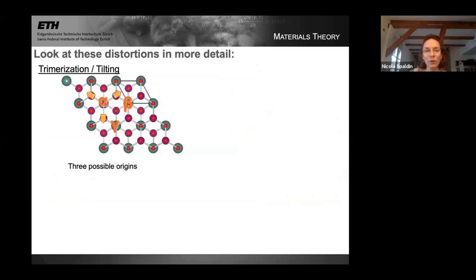to trimerize around. Then origin beta, which was previously equivalent to alpha, is excluded as a trimerization center, because to trimerize around beta, this oxygen would have to go up and left, and it's already used up going up and right. And likewise, origin gamma is not available as a trimerization center, because that would require this oxygen to go up and left, and it's already used up going down. So I have three possible choices of origin that I can choose to trimerize around. So this should give me three domains, right? I have three possible places I can choose, kind of like three choices of angle in the mexican hat potential example.